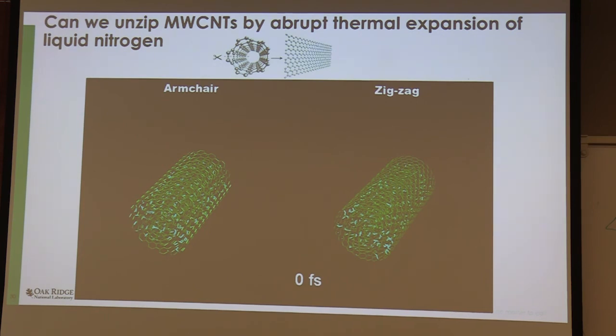Graphene became the more exciting one, because if you can control the width of a graphene ribbon precisely without any defects, you can control the band structure. You can make it a semiconductor. And then you can put it in a transistor. You can do all sorts of things with it. But how to control the width was a real issue. So we thought, well, why don't we just use carbon nanotubes and just unzip them? You cut a carbon nanotube, either a zigzag or an armchair, down the middle, and you'll get a ribbon that's exactly the width of the diameter that the nanotube was, right? Just unfold it. Perfectly controlled.